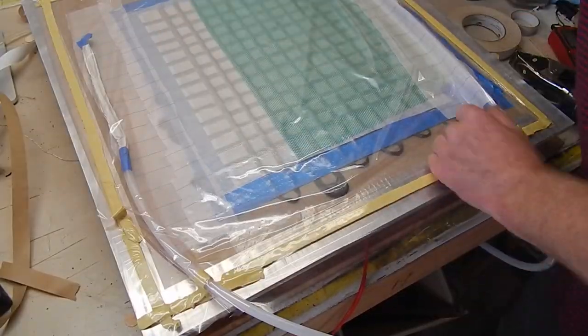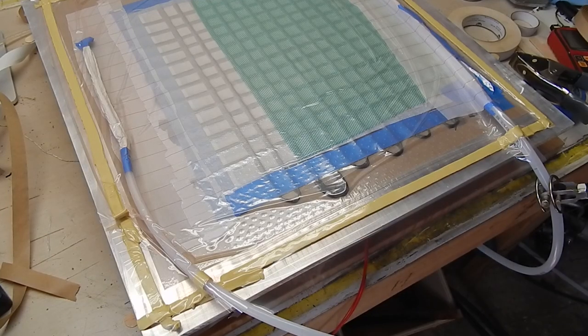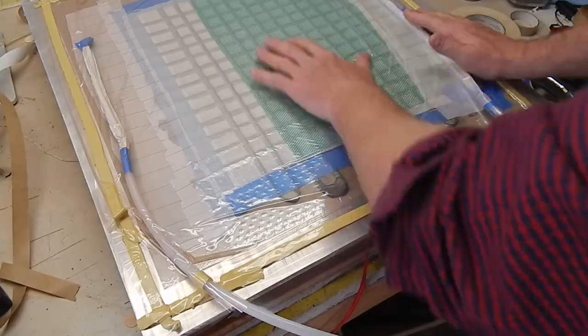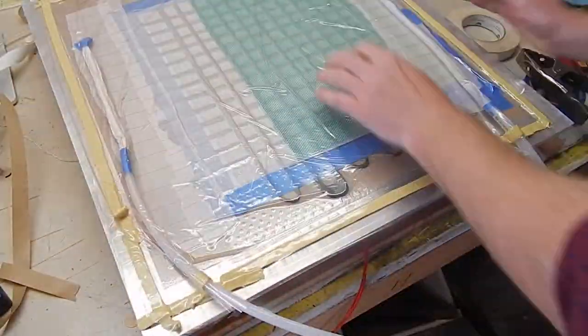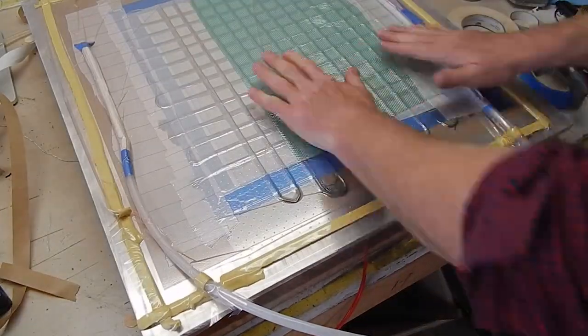Got the bag pulled down. Got it down to about 2 millibar. Didn't seem like it was leaking. Still a little ugly though around all those pleats. Should definitely have been about 200mm bigger in each direction.